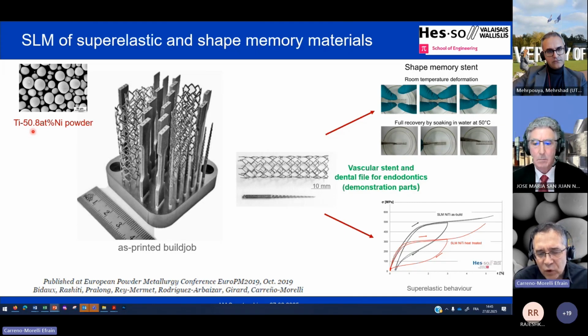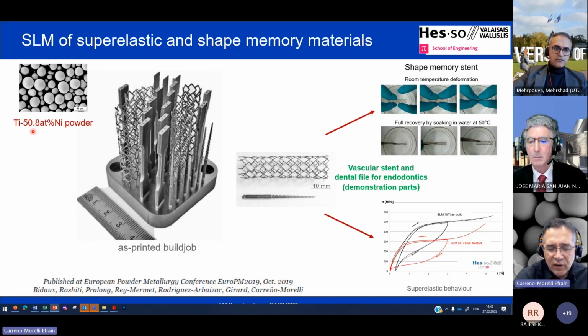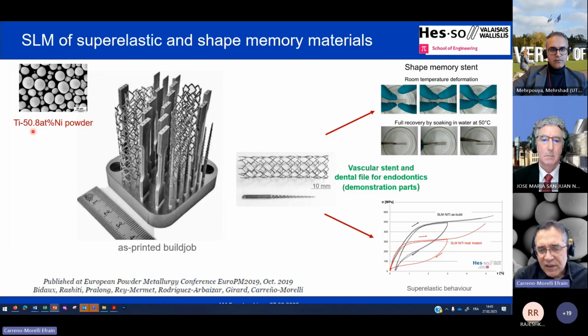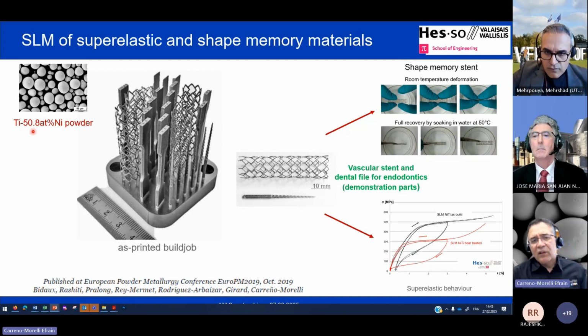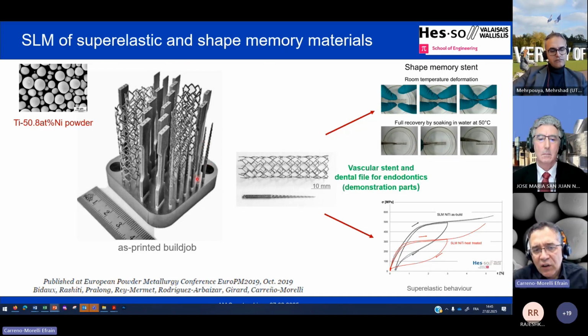The powder came from rods we acquired, and we request atomization of the rods by partners, experts in the field. Then we obtained nice powder with good flow properties and purity, and we use it to feed our machine. We use a reduced working table. The machine has the standard build plate of 125 millimeters inside, but this reduction is with 50 millimeters inside, which allows us to use a small amount of powder.